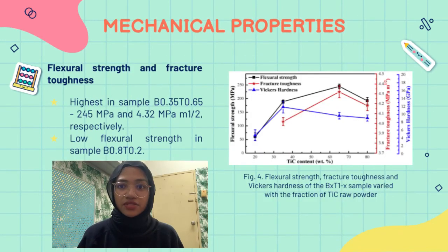The highest flexural strength and fracture toughness are found in sample B0.35T0.65, at 245 megapascal and 4.32 megapascal m^1/2 respectively. The sample B0.8T0.2 has a relatively low flexural strength, which can be attributed to its high porosity. The well-distributed titanium diboride and silicon carbide particles in sample B0.35T0.65 act as barrier reinforcement, strengthening and toughening the material.